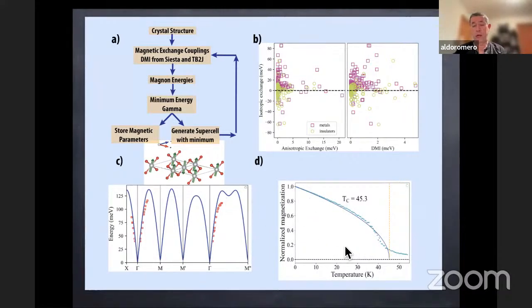The other quantity that we can compute is how the magnetization changes as a function of temperature. We can define the so-called transition temperature, the Curie temperature. What is important about that is that if you are going to use a magnet, you care not only whether the magnet happens to be strong, but also what the temperature regime is where you can use that magnet. That's very, very important. In the case of two-dimensional materials, most of the magnets that people have been able to synthesize up to now do not have a temperature higher than 300 K.